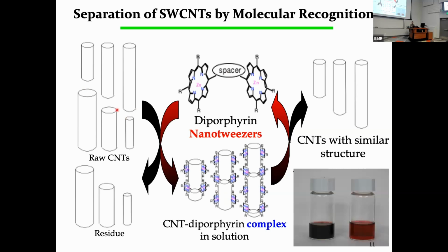So there are various kinds of carbon nanotube, with different diameters, different lengths, and a different alignment of the phenyl ring. And this plays a very important role. This is a host molecule to recognize the structure of the carbon nanotube. This is the first generation we called diporphyrin nanotweezers. Here you can see the two porphyrin units. Porphyrin itself has a very great affinity toward the surface of the carbon nanotube. Commonly we use the word pi-pi interactions.